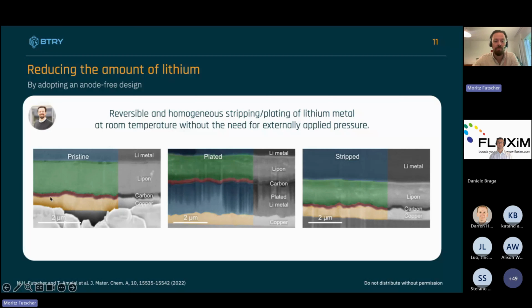And in this case, we developed interlayers and tested different interlayers to have homogeneous growth. And we could find one interlayer, in this case carbon, where indeed the lithium metal was able to grow very homogeneous here in a thick layer. And you even see that the shape of the current collector here is still visible up here, which really shows you that this lithium metal grows in a very homogeneous manner.